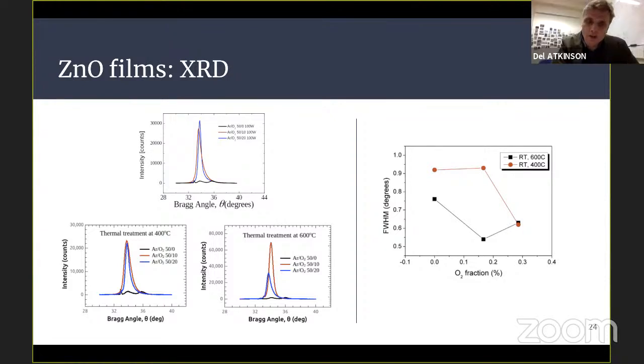Okay. That's good. So when I look at the XRD plots on the left, at the one at the bottom on the left, on the right hand side of those, it looks like the peak is shifted for different conditions of your deposition. So what's your interpretation of that? We believe there were some internal strains due to the deposition. That's because there was some shifting. That made us think that we needed some thermal treatment in order to relax these strains. So we did this thermal treatment at 400 degrees, which made the peaks a little bit more symmetric. And at 600 degrees, we actually created some deformations, so this maybe was not the most effective one. So that's why we decided to go with the lower temperature. Okay, thank you. I think I should move on because I'm asking quite a lot of questions here.